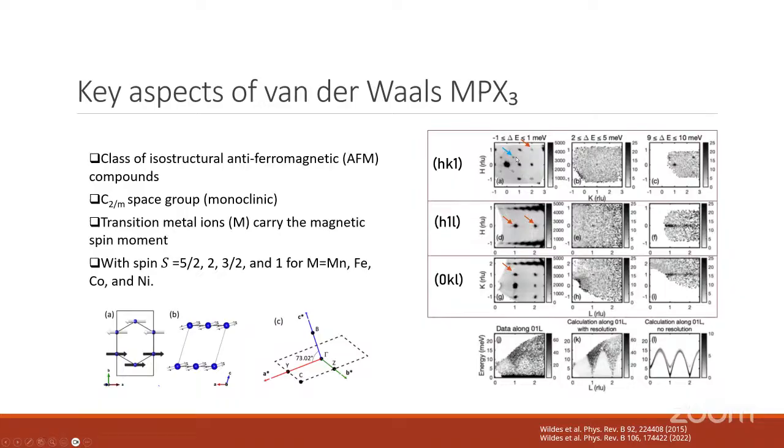However, there are also some other peaks which are not the 010 magnetic peak, but are still showing in the diffraction pattern like this one. This is because the system has a 120-degree rotation in each domain. When you grow your sample, the sample may contain different domains, and each domain has a 120-degree rotation because this is a hexagonal structure.